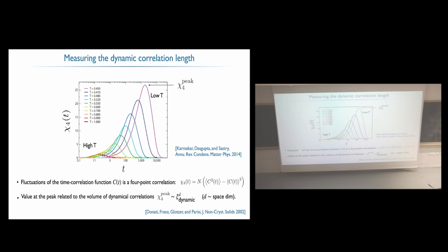So if you want to know the heterogeneity, what you can do is, I plotted the correlation function. It's something that decreases on a time scale that's changing. But if you want to know a bit more about that, and in particular some length scale, you look at the fluctuations of this quantity. And actually you get these kinds of curves. So this is this 4-point function.